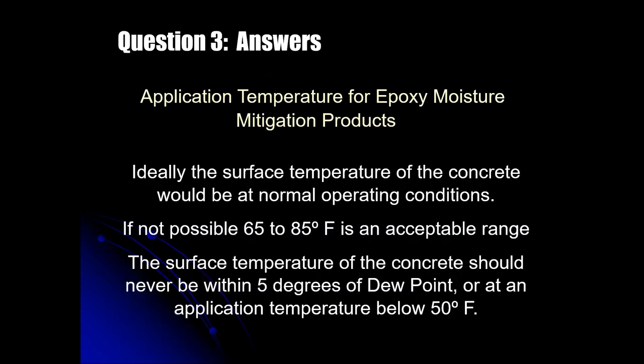Ideally, when you're applying a moisture mitigation system, the surface temperature of the concrete would be at normal service conditions, but that's not always possible. In fact, it's seldom possible in new construction. But you really do need to not be below, well, in my personal opinion, I don't want to be applying an epoxy on a concrete substrate that's below 50 degrees Fahrenheit. Ideally, the ideal range is between 65 and 85.